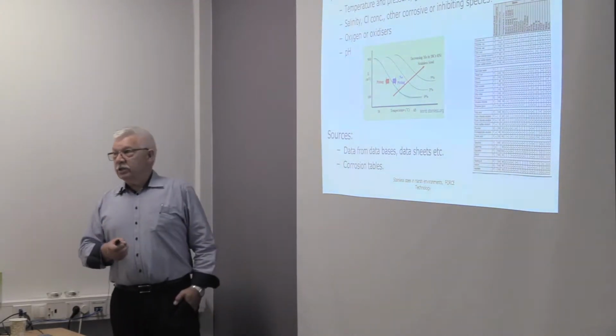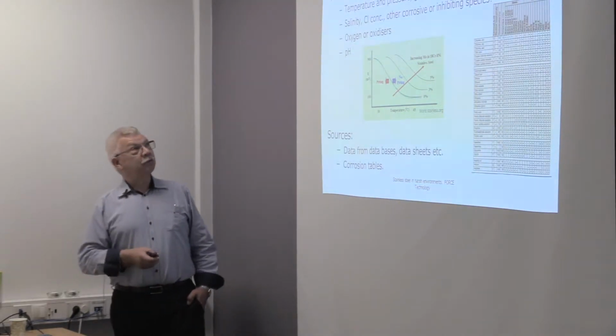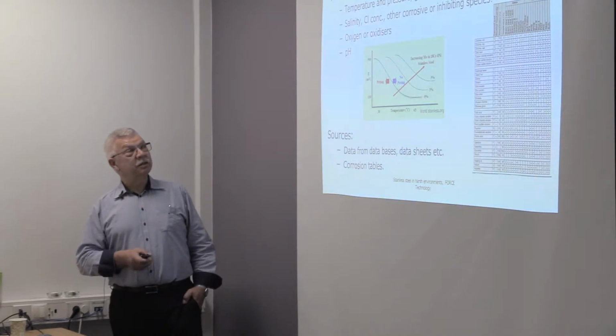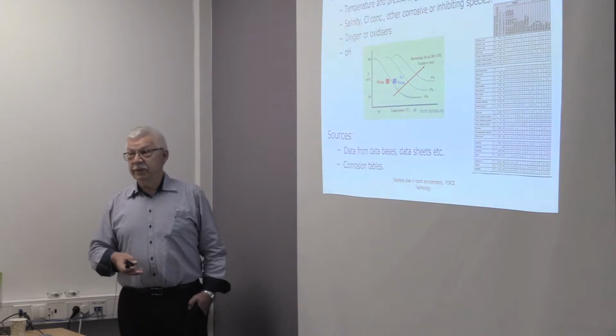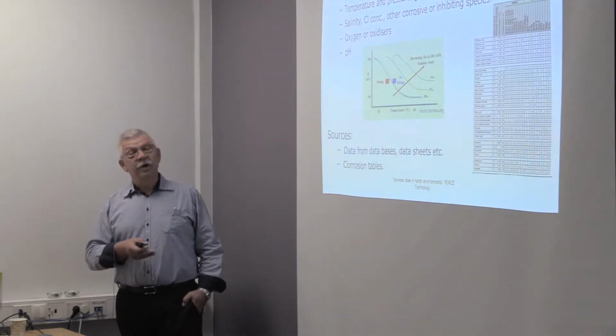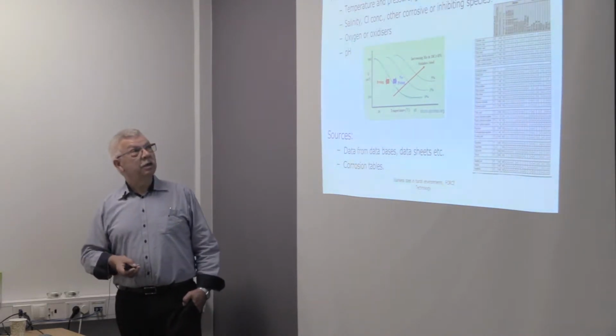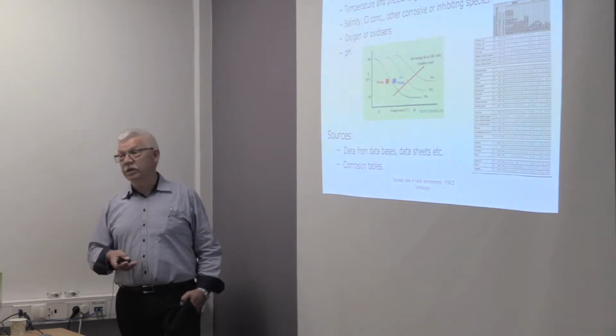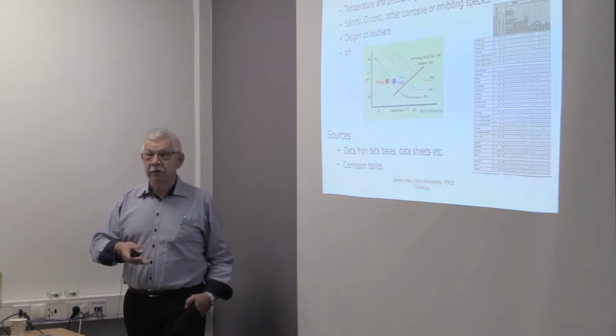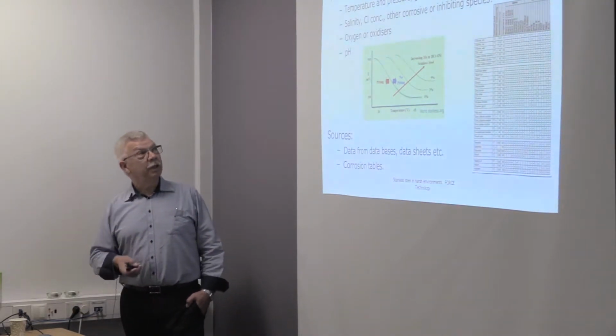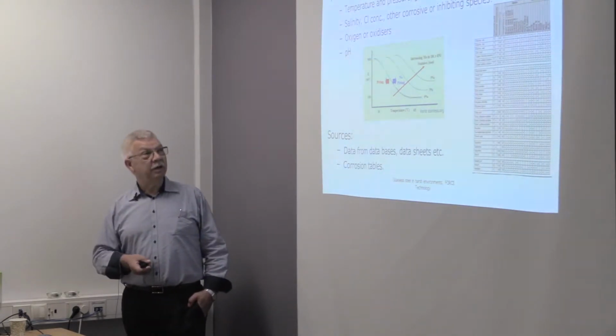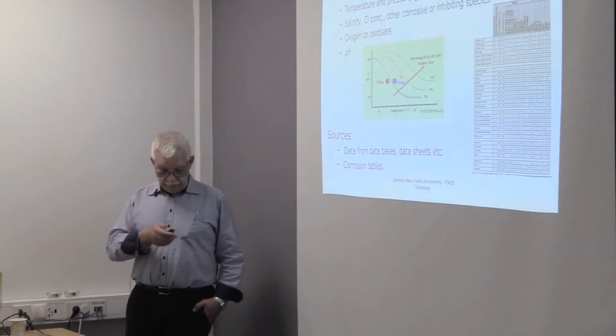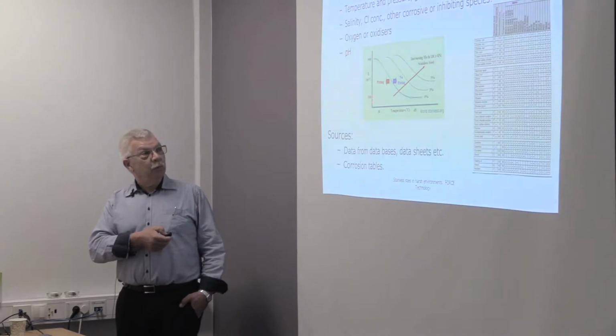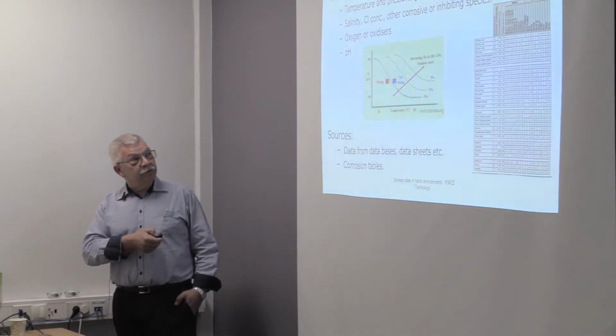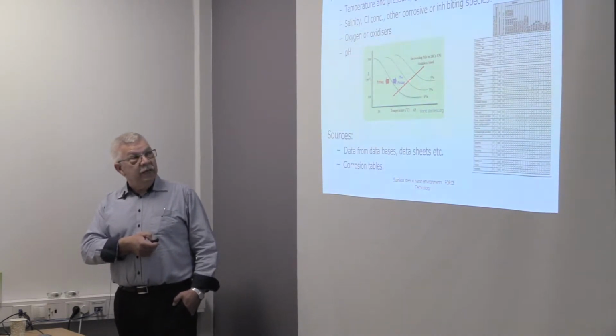The primary parameters that we look into to see whether that will be the case or whether we will have corrosion is to define our basic media by the temperature and the pressure. Will it be gas? Will it be wet? Will we have a certain amount of salts or chlorides? Will we have other corrosive or inhibiting species in the media? Will there be oxygen or other oxidizers that can act as oxygen? What will the pH level be? That we need to know to define our media. And if we have an increase in temperature, as shown here, at a certain level of corrosivity, then we will need more stable or higher alloyed stainless steel to withstand that without having corrosion.